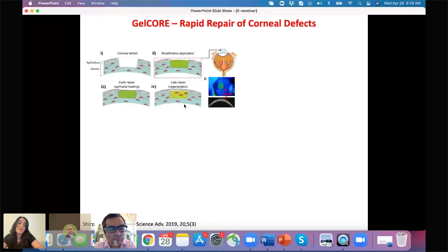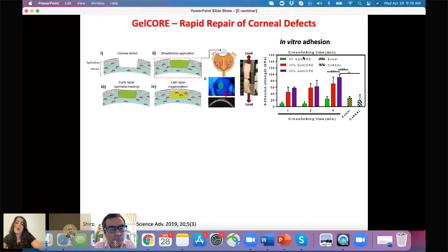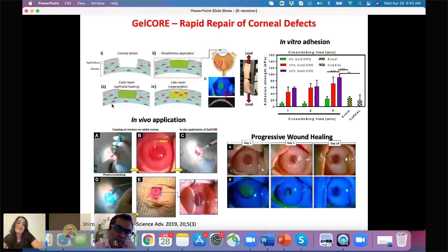So in this paper we published a few years ago, we show that the properties of GelCORE can be tuned by changing the photo cross-linking time or the composition of the hydrogel. And we can reach adhesion strength higher than commercial bioadhesives. And we also apply an optimized formulation of GelCORE in vivo. This time we create an incision on the rabbit cornea by using a biopsy punch. Once we form the defect, the hydrogel was delivered as a liquid, and then we photopolymerize it by visible light.